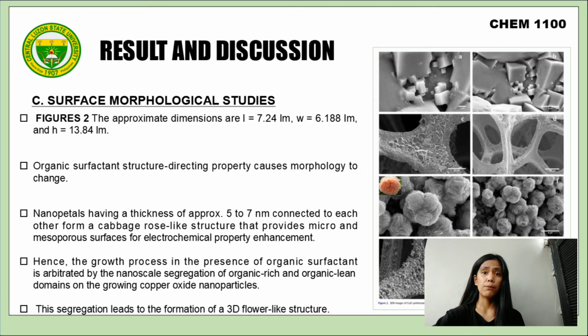Triton X-100 molecules contain polyethylene oxide and aromatic hydrocarbons, and these molecules are responsible for the formation of hydrophobic and hydrophilic regions. Hence, the growth process in the presence of organic surfactant is mediated by the nanoscale segregation of organic-rich and organic-lean domains on the growing copper oxide nanoparticles. This segregation leads to the formation of a 3D flower-like structure.